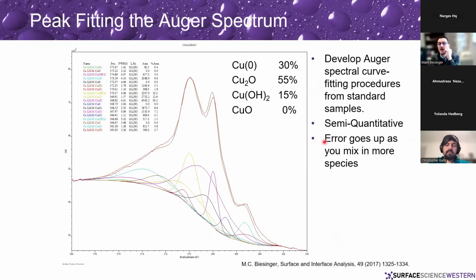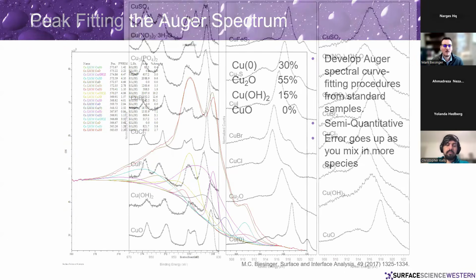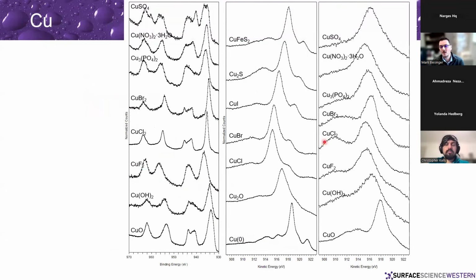So we're going to look at those sorts of things and try and use those analyses. And so what we've done is curve fitting of the Auger peak. And so that allows us to, again, semi-quantitatively or even fairly quantitatively pull out what species we have that we aren't able to do by looking at just the 2p spectra. We've developed this for a wide range of copper species, and there's a lot of information we can pull out of copper.